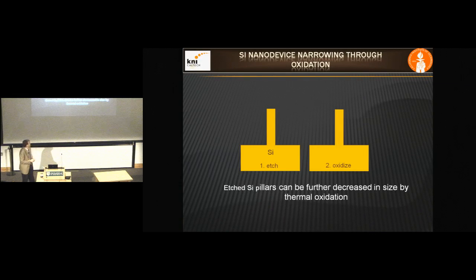Now we can think about what do we do if we want to make electrical measurements? Well, we can oxidize it. So we start with something that's maybe 10 nanometers or so in size, and we oxidize it. We make it smaller, shrink it down. So the silicon now is encapsulated by an oxide layer. And what's interesting is this oxide is less dense and thicker and bigger than the silicon. So the silicon starts and it forms the oxide. The oxide is bigger, so it'll put the oxide under compressive stress and the silicon under tensile stress.